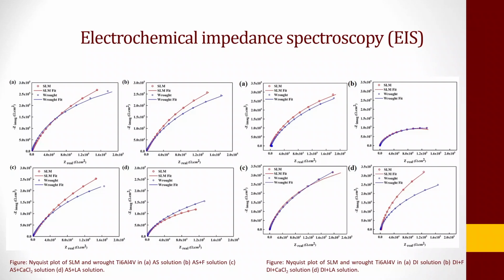Similarly, when we did the Nyquist plot of SLM and ROT in DI water, DI fluoride, DI calcium chloride, and DI lactic acid, you could see that, for example, in DI lactic acid, the additively manufactured sample is behaving better as compared to the ROT. And when you look at the lone DI solution, again, you observe a similar type of behavior where the additively manufactured curve is behaving better as compared to the ROT material.